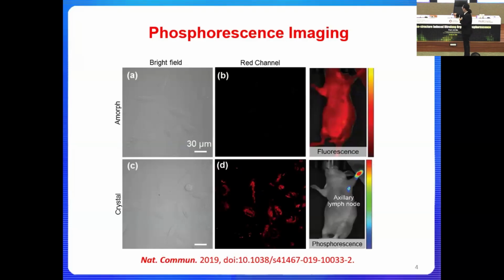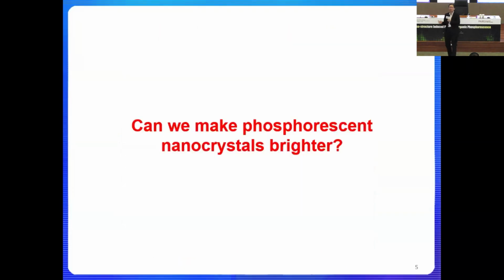Now, if we make the molecules into small nanocrystals, then we are able to have cell imaging with extremely low background signal, because they are captured at a different lifetime frame. And more importantly, now we really don't have any background signal from the animal, so that we can differentiate the signal of interest from the background. With this initial success, we asked ourselves, what can we do to make the phosphorescent nanocrystals much brighter? The first step, very simple: we went to the literature to see which molecules actually show phosphorescent emission, so that we can synthesize them and make them into particles.